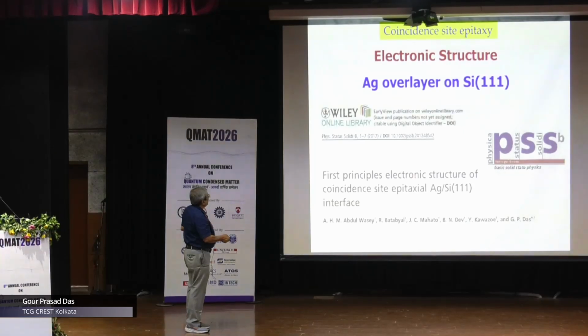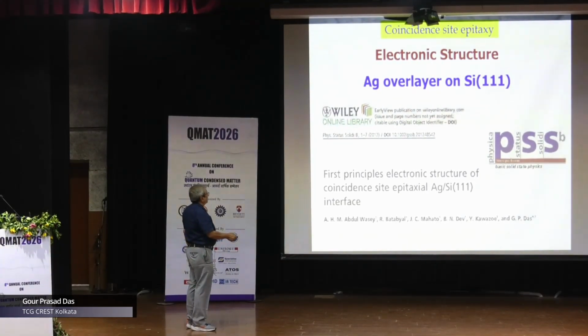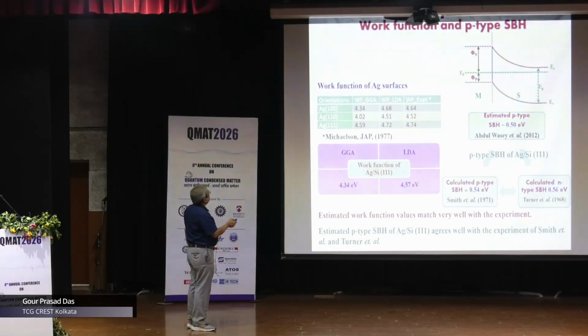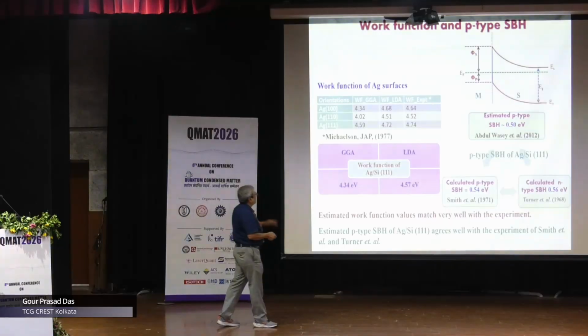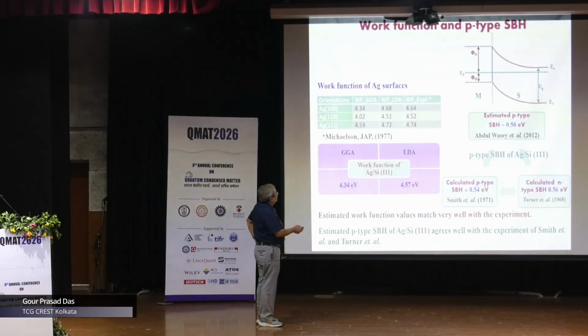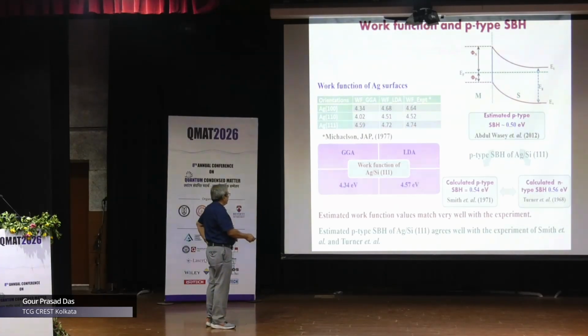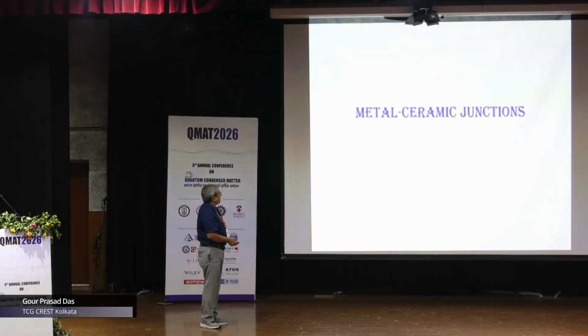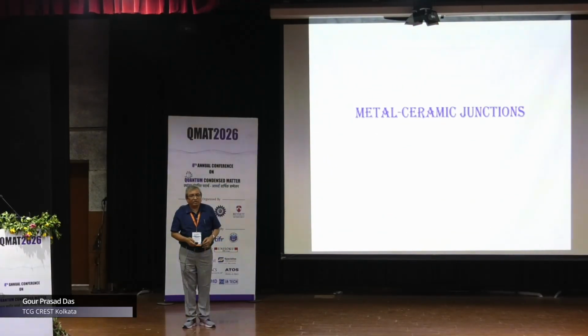So we did the first principles electronic structure of coincidence site epitaxy silver silicon 111 interface. This was published sometime in Physica Status Solidi. Okay, so again we did the detailed calculation. Look at just the numbers I would like to tell you. The estimated p-type Schottky barrier height which we got for this system is 0.5 electron volt, whereas the experimentally determined values are 0.54 and 0.56 by two different groups. So that is a very good matching, I will say. Okay, so the estimated work function values as well as the estimated p-type Schottky barrier height both agree well with the experiments.